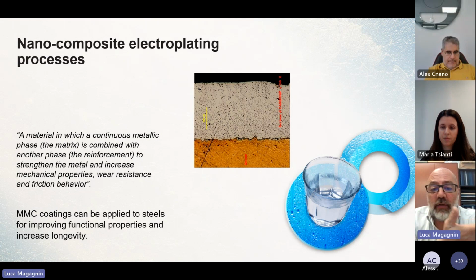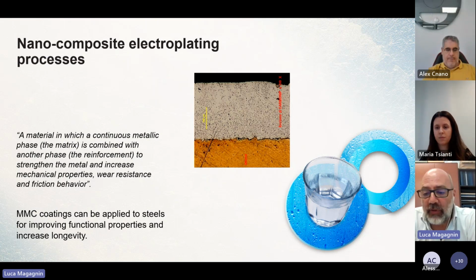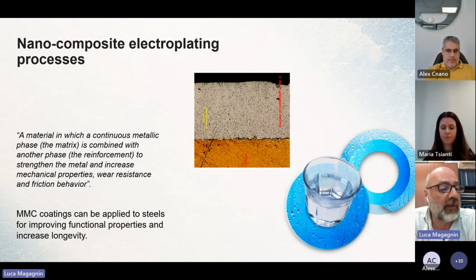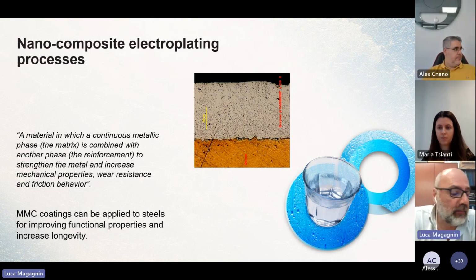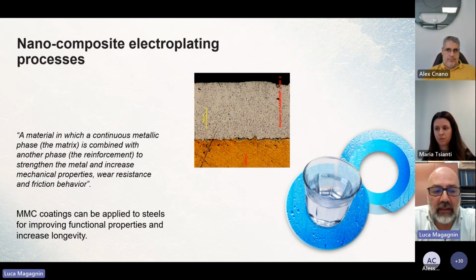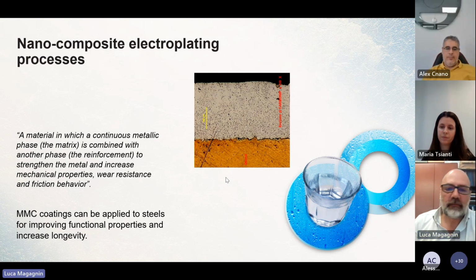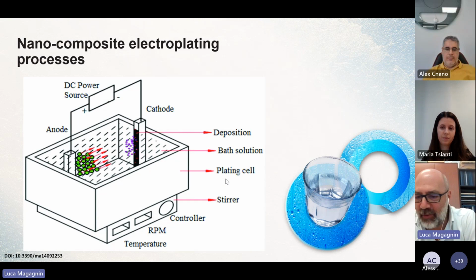Another possibility is, for instance, to introduce particles which can be classified as solid lubricants. If we want to have not only wear resistance but also a low friction coefficient, we can co-deposit carbon-based particles, for instance layered compounds like molybdenum disulfide, tungsten disulfide, and so on. And so again, combining the properties of the dispersed phase, the particles, with the properties of the matrix. If I go too long, Maria, please stop me.